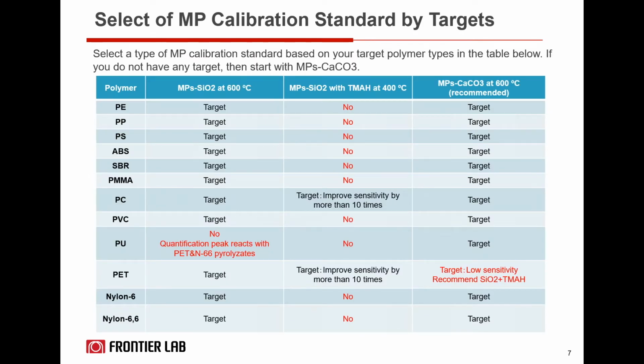So now that you have that set with 2 or 3 different types of calibration standards, how would you choose which calibration standard you would like to use as the first step? This table here can guide you to select the appropriate microplastic calibration standard. You can select the type based on your target microplastic polymers. Now, if you don't have any targets at first, we suggest that you start with MP's CaCO3 standard that can target pretty much all the 12 polymers, but with low sensitivity to PET.